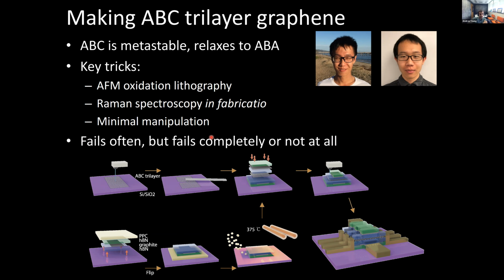And so it fails often still, but one of the great things about this is that it tends to fail completely or not at all, in the sense that once you stabilize an ABC, it's possible to stabilize a purely ABC flake, and as you'll see, then these systems have extremely low disorder.